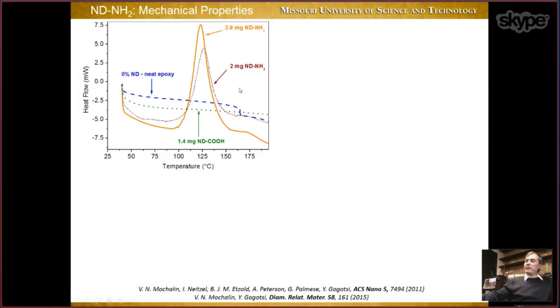So first of all, we know that we have covalent bonds between amino groups and nanodiamond surface. I showed you on the previous slide, we proved it with IR spectroscopy. Now, how can we monitor the reaction of amino groups on nanodiamond with epoxy resin? We can do it by using differential scanning calorimetry. Differential scanning calorimetry shows you heat evolved during the reaction. So when we mix nanodiamond with epoxy, and if there is a reaction, we expect to see heat evolved, and we can measure that heat. And in a DSC experiment, the amount of heat corresponds to the area of these peaks, which are shown here. So this is what we are after.